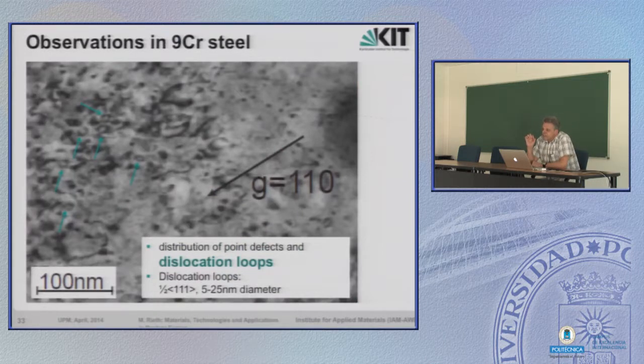Okay, so far, interstitial atoms, vacancies, and clusters of both kinds are defects which occur after irradiation. But if you have a close look at this TEM image, you see small circles here at the tip of these arrows. They are also rather tiny, in the range of a few to about 20 nanometers. This is a very specific kind of another defect in metals after irradiation, that's dislocation loops. If you remember our picture from the morning of this complicated dislocation network, then this is another species of dislocation. These are tiny loops which also form as a result of irradiation.